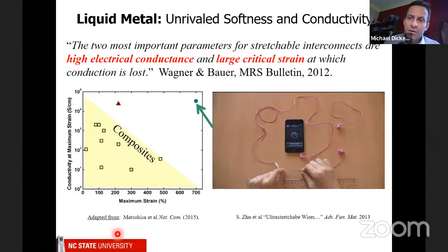So as you can hear from this video, there is no degradation in the volume or the sound quality. And we were able to get a wire that's stretchable, like a piece of rubber, but has electrical properties like metal. So this kind of gives you the best of both worlds. You get stretchable and conductive.